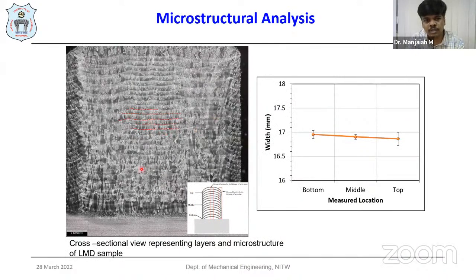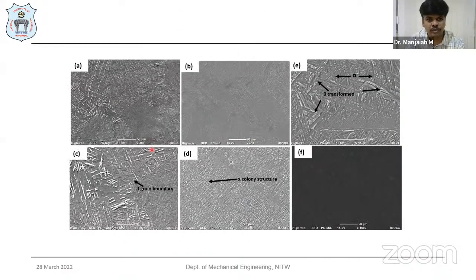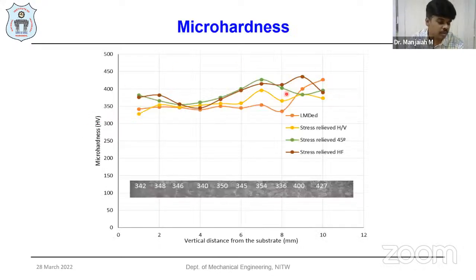This will give us the overall view of the macrostructure of the components, how the columnar grains are towards the build direction as well as in the edges. And if you see the cross-sectional micrograph of the magnified view of this titanium, it consists of alpha grains, beta grains, beta at the grain boundaries and alpha colony structures, as well as beta transformed grains visible in this microstructure, and it is almost similar to that of wrought titanium alloys.